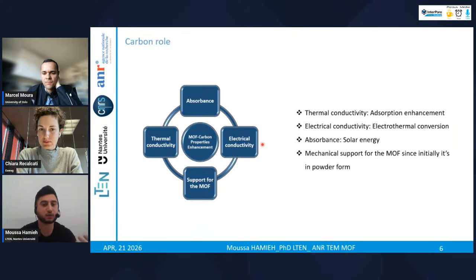This allows electrothermal conversion in situ through Joule effect heating, by passing a current at low voltage and current. It's also compatible with photovoltaic PV, so it's a renewable energy source. It also enhances the absorbance of our material, the MOF. So it can also absorb direct solar energy, which will help us in the thermal regeneration.